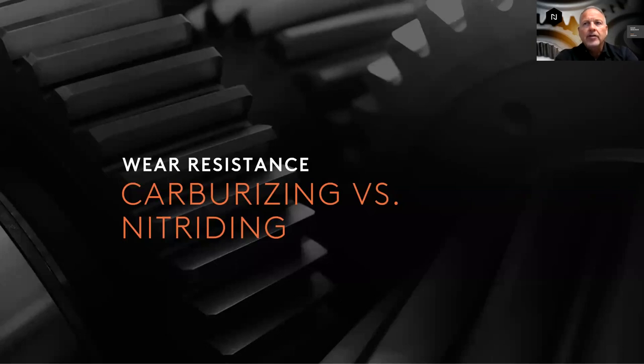Jack, I'd like to add here that the difference is that the alloying elements that are used actually combine with the nitrogen for the hardness. So as Jack mentioned, that's your chromium, your vanadium, your moly, et cetera. Whereas you saw on the carbon profiles there, the carbon steels have very little alloying elements. And those elements that are put in there are used for core properties primarily, because the carbon is not combining with any other type of the alloy.